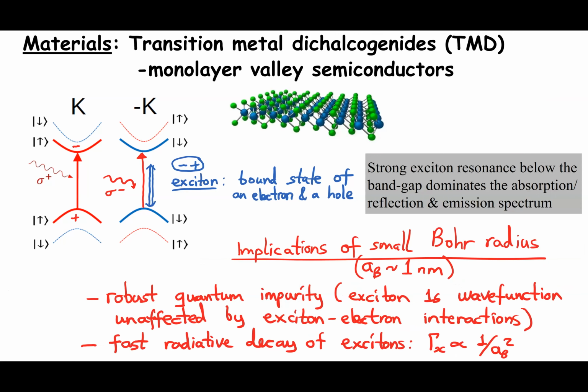I showed you this very small Bohr radius, which has several implications. And in the context that we are discussing, the most important one is that we will be considering itinerant electrons in the semiconductor. So we told you about excitons in the absence of electrons, but if I introduce electrons, provided that the Fermi wavelength is large compared to the size of the exciton, we can argue that the exciton wave function would remain robust.